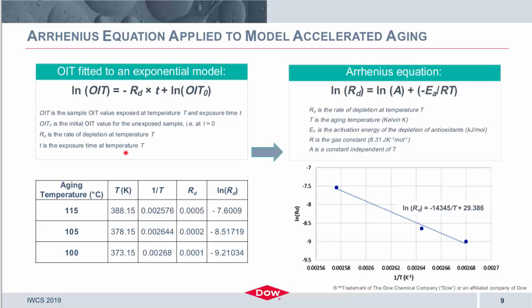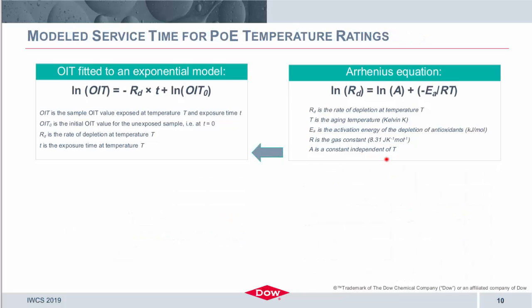Once we have our RD from the exponential fit, we're able to put that into the Arrhenius equation and fit, again, another model where natural log of RD with respect to 1 over T in the given aging time, where we then are showing the equation similar to the Arrhenius, in which case now we're able to translate that information and fit it back into that exponential model to ultimately determine a predicted service time.